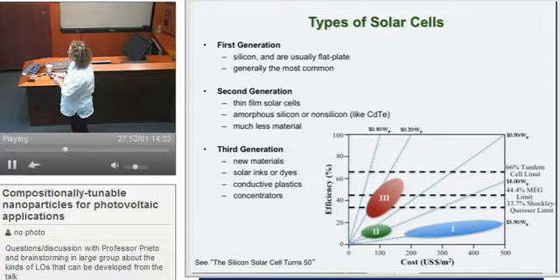So here I'm showing you the cost in US dollars per meter squared of the solar panel versus the efficiency, and these are calculated bubbles. So bubble 1 are first generation materials. These are silicon, they're usually flat plate. These are the most common, and they range anywhere from $3.50 per peak watt down to about $1.25.